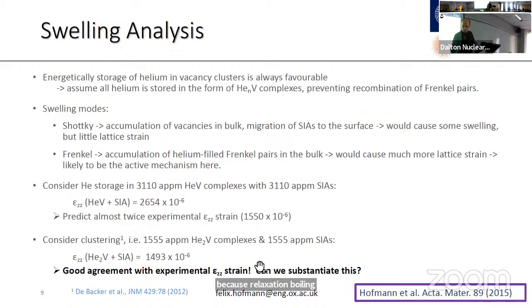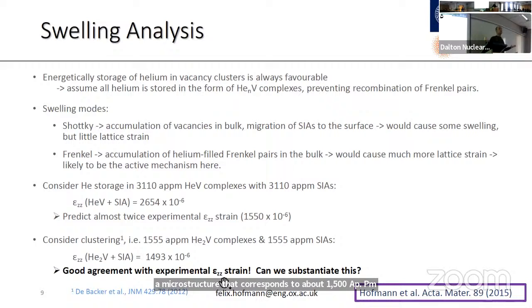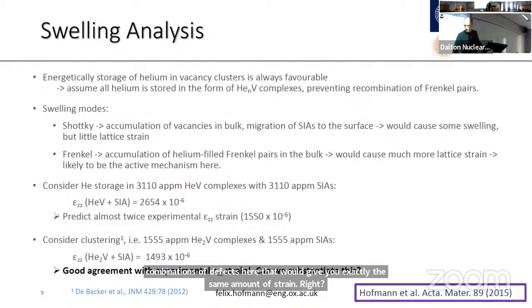We can do this, and we can see that if you had a microstructure that corresponds to about 1,500 appm of interstitials and helium-filled vacancies, then this gives something that's quite close to the measured strain. Right. Well, we can think of lots of possible combinations of defects here that would give you exactly the same lattice strain, right? So this doesn't really help. So how can we substantiate this?